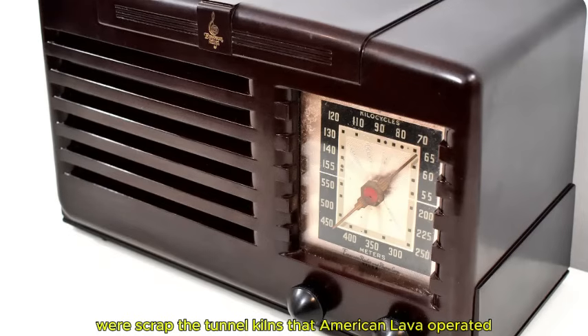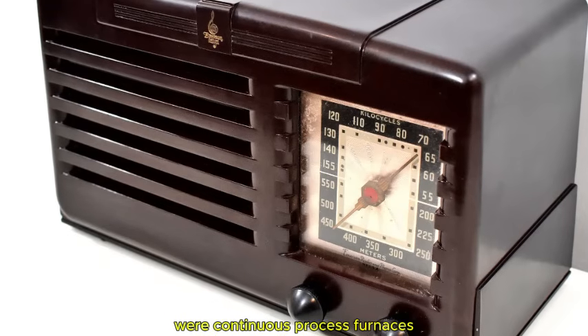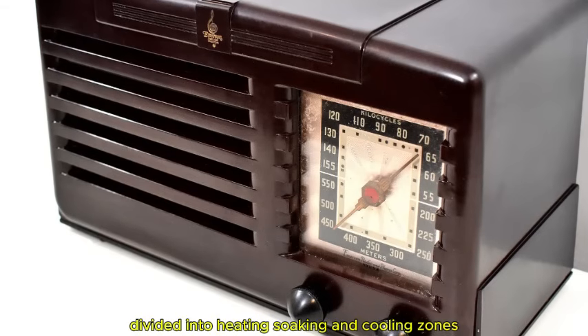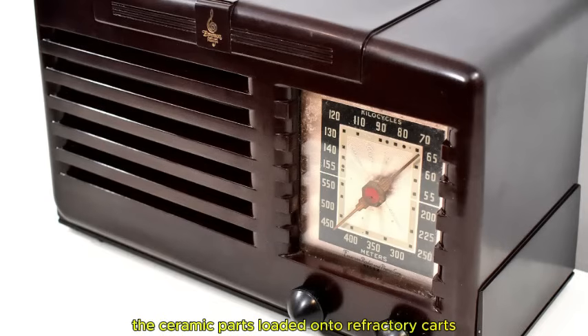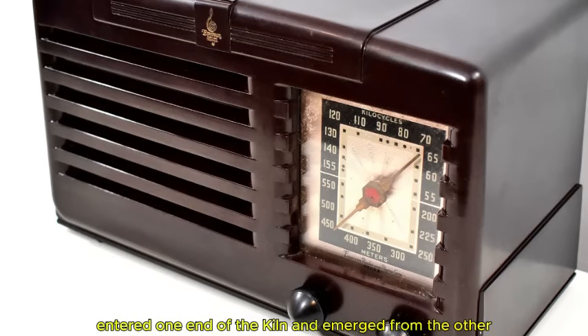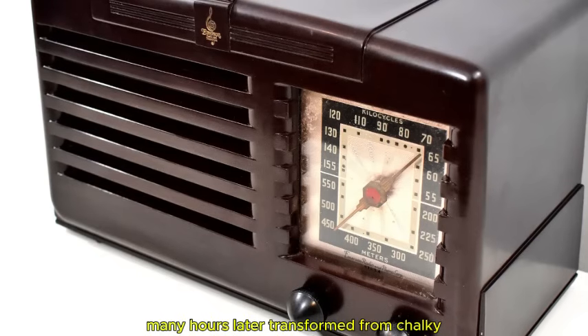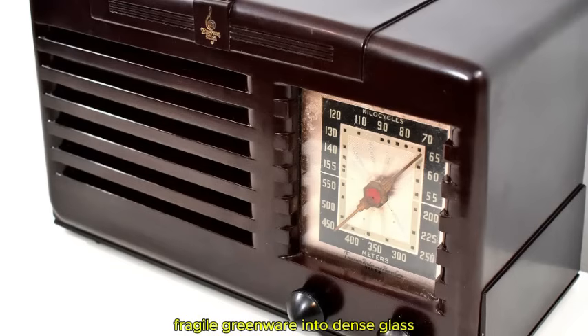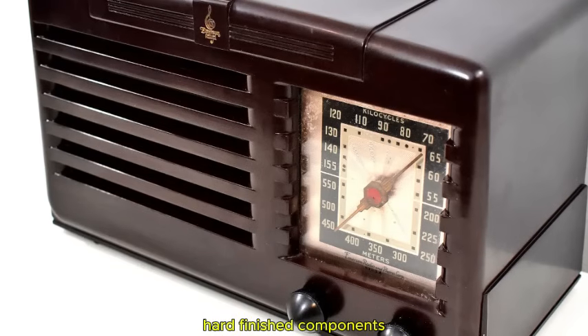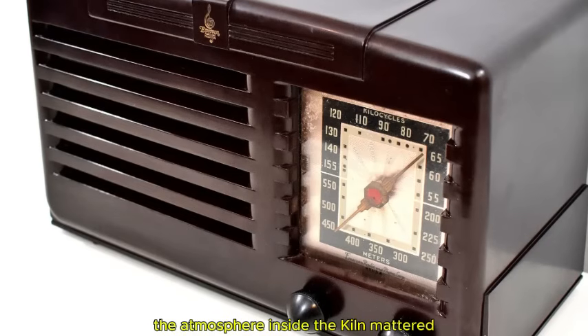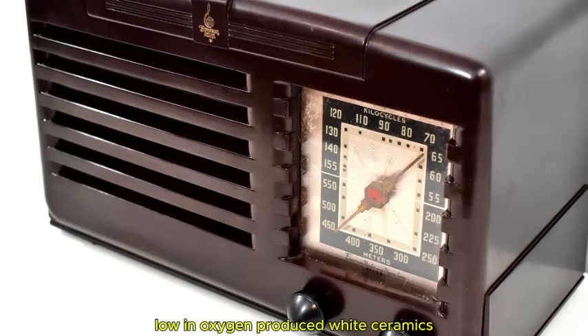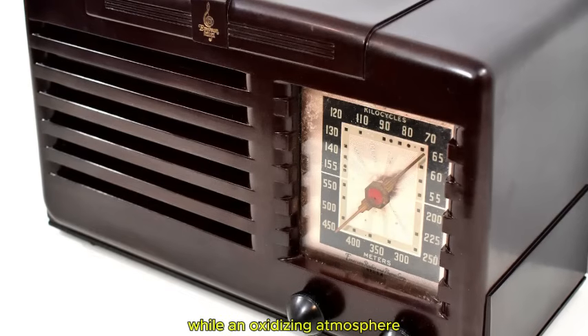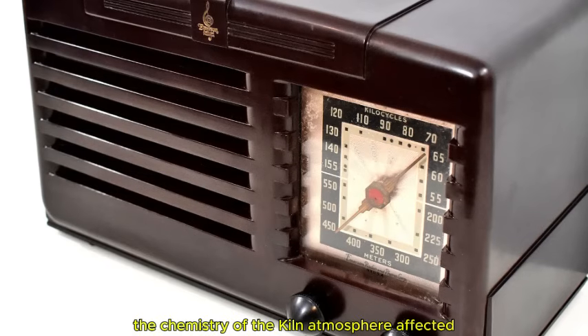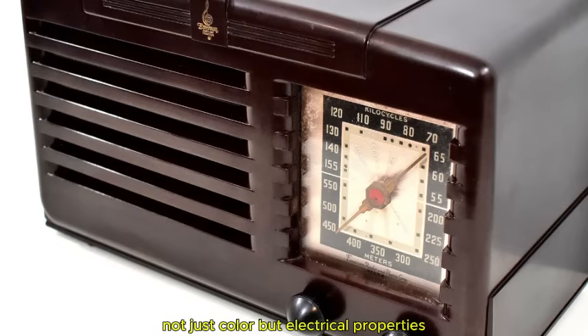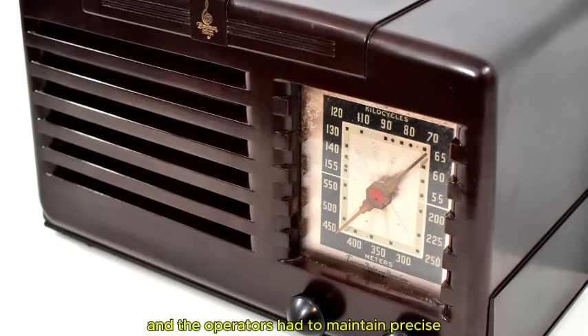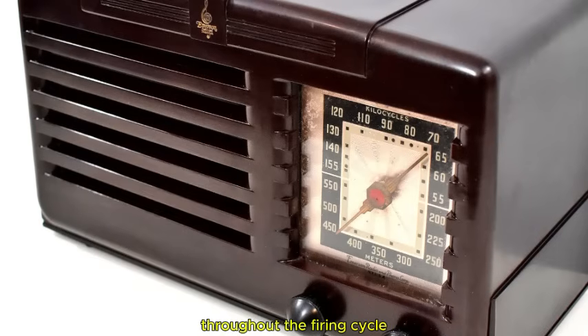The tunnel kilns that American Lava operated were continuous process furnaces, some of them over 100 feet long, divided into heating, soaking, and cooling zones. The ceramic parts, loaded onto refractory carts, entered one end of the kiln and emerged from the other many hours later, transformed from chalky, fragile greenware into dense, glass-hard finished components. The atmosphere inside the kiln mattered. A reducing atmosphere, low in oxygen, produced white ceramics, while an oxidizing atmosphere produced a yellowish color. The chemistry of the kiln atmosphere affected not just color but electrical properties, and the operators had to maintain precise control of the gas flow and combustion conditions throughout the firing cycle.